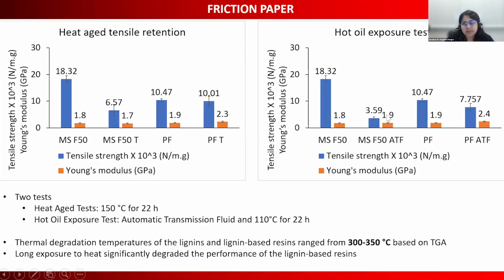oil exposure test, similar results are seen. The miscanthus resin significantly drops strength after it's exposed to the automatic transmission fluid at temperature and time, whereas PF also drops slightly, but it maintains 70%, 77% of its strength essentially. So this told us that our resin was not thermally very stable.